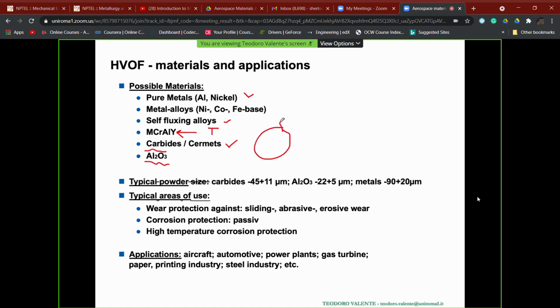In this case, as we have said, but we need to repeat, our particle is made of a matrix based, for example, on a metallic alloy like nickel chromium, just to give an example, and other small ceramic phases, which are, for example, tungsten carbide. So we start from pre-alloyed particles, which can also be fabricated by gas atomization or by mechanical milling, with the methods that we discussed when we talked about the sintering technology for ceramic materials. In this case, we do not expect to experience any melting of the carbide, of the ceramic phase in the cermet materials. What is going to be melted is the metallic phase.